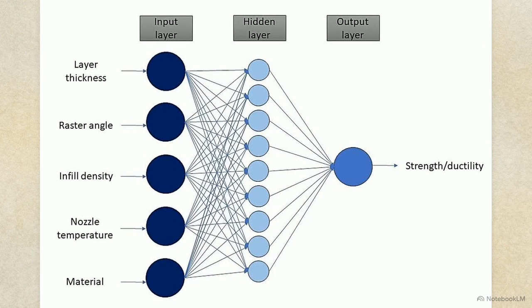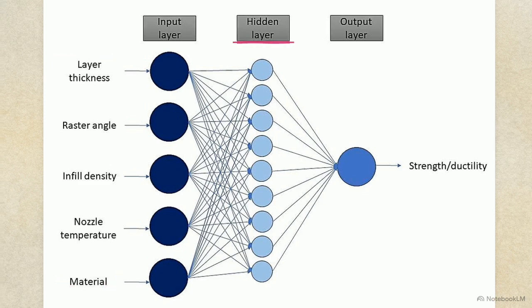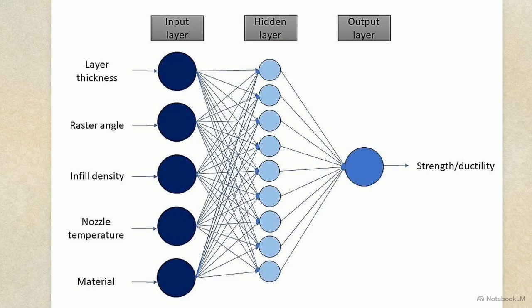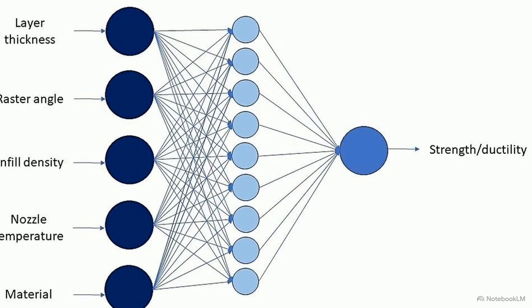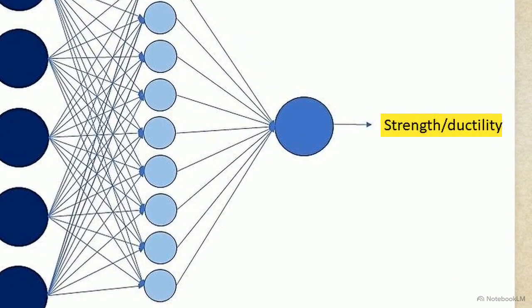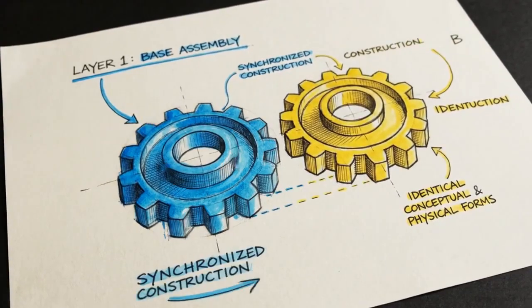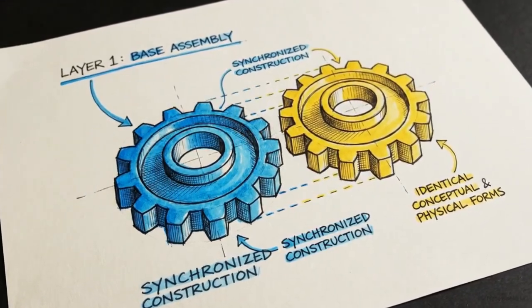The network uses a Levenberg-Marquardt algorithm combined with backpropagation to optimize the weights of its connections based on the experimental data. The architecture receives 5 normalized inputs: the material type, layer thickness, raster angle, infill density, and nozzle temperature. Those inputs feed into a hidden layer consisting of 9 distinct neurons. This hidden layer applies a tangent sigmoid transfer function, processing the complex, nonlinear physical relationships we observed in the parameters. Finally, the network synthesizes these interactions to generate a single output targeting ultimate strength or ductility. This architecture effectively acts as a digital twin for the printer. It simulates the physical shear and load behaviors established on the testing rig.